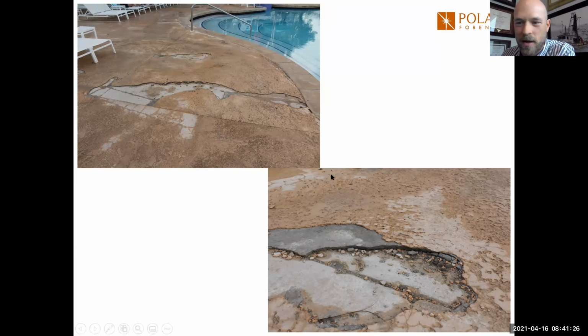To give you an idea of what you're looking at, the light gray material is the original concrete deck. That darker gray material is that thin-set patch, which I mentioned was used to cover imperfections and to re-level the surface. And that pink salmon color is that cool deck overlay. So, we were hired by the resort to investigate this issue, to determine why this was happening, and to provide repair recommendations.